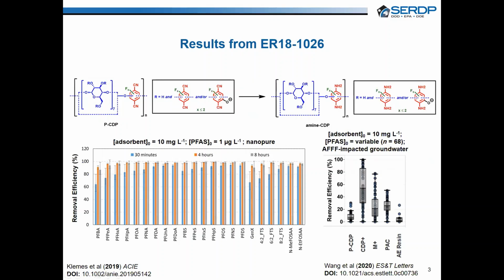Over the course of SERDP project ER18-1026, we synthesized dozens of novel cyclodextrin polymers, looking at different chemical cross-linkers, different cross-linking density, incorporation of co-monomers, and so on. And some of the dozens of cyclodextrin polymers that we synthesized performed really well for removing PFAS from water. I'm showing one example here that was produced from our first cyclodextrin polymer by means of a post-synthetic reduction reaction that transformed the nitriles on the crosslinker to primary amines that could be positively charged at neutral pH.